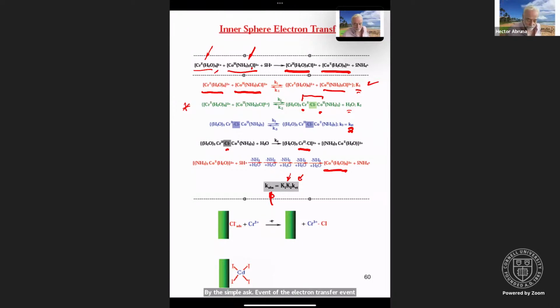If we were looking at an equivalent electron transfer event at an electrochemical interface, so for example, the oxidation of chromium 2 to chromium 3 can be mediated by an adsorbed layer of chloride. So chloride here becomes the bridging ligand between one of the reaction partners, which is the electrode surface, and the chromium itself. There are other ones. So for example, tetraiodo-cadmium, so this is CdI4. On a mercury surface, it adsorbs with two iodides basically contacting the mercury surface, bringing the cadmium to the inner part of the interface.